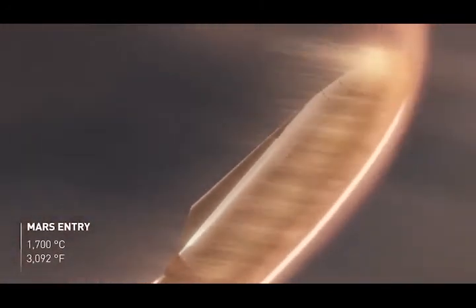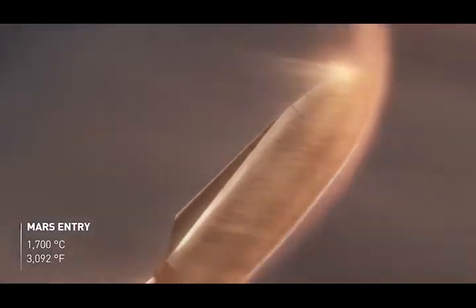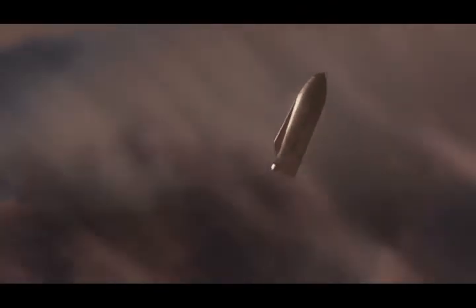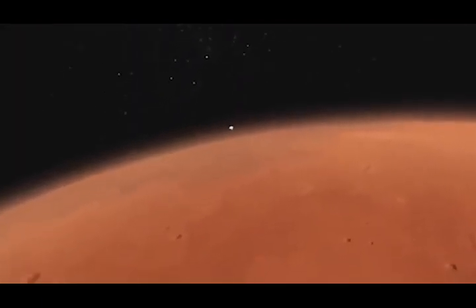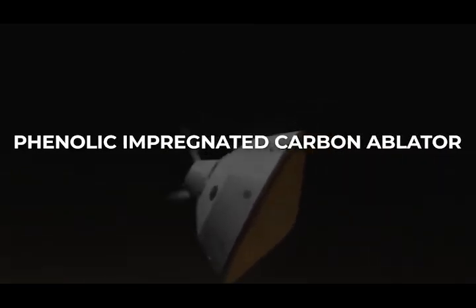The Starship can expect to enter the Martian atmosphere at speeds of up to 21,000 kilometers per hour and experience temperatures up to 1,700 degrees, well above the maximum service temperature of both aluminium and stainless steel, but we have ways of leaching some of that heat away before it can heat the metal. The Curiosity rover utilized a phenolic impregnated carbon ablator, which is extremely light, has a low thermal conductivity, and can resist extreme temperatures of up to 1,930 degrees.